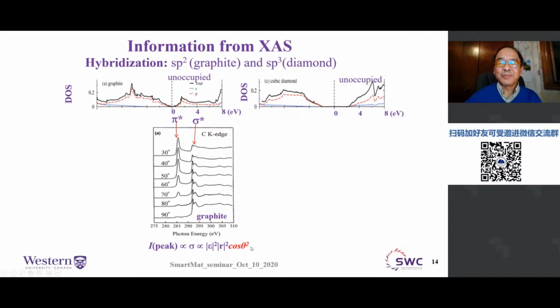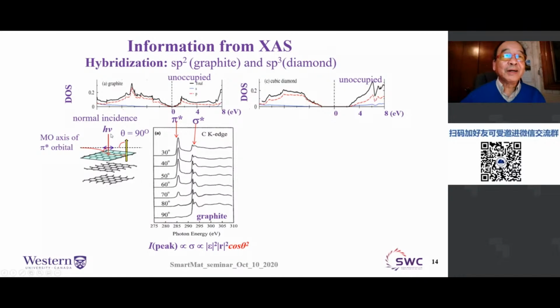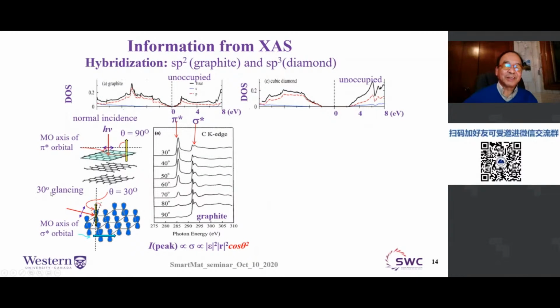So this angle, in fact, is the angle between the polarization and the molecular axis of the orbital. Let me just give you an example. In the case of a normal incidence on the synchrotron with polarization lying this way, and that is the axis of the molecular orbital, then it's 90 degrees. And obviously, cosine 90 equals 0. So when the angle is 90 degrees, we don't see any pi star transition, right? If you increase the angle to more grazing, like 30 degrees, cosine is now approaching 1, which is 0 degrees, and the intensity increases as you increase the angle.